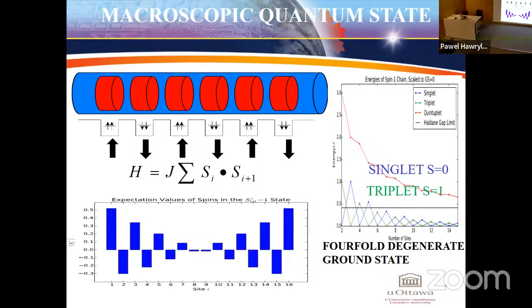We look at the expectation value of spin. So this is an expectation value of spin in a ground state, as a function of site. And now if we look at the edge, we see that the spin at the edge is half. We started with spin 1s, but a collective state of this very large quantum system is such that at the edge there is a quasi-particle with spin 1/2. There's another one with spin 1/2 here, 2 spins 1/2.